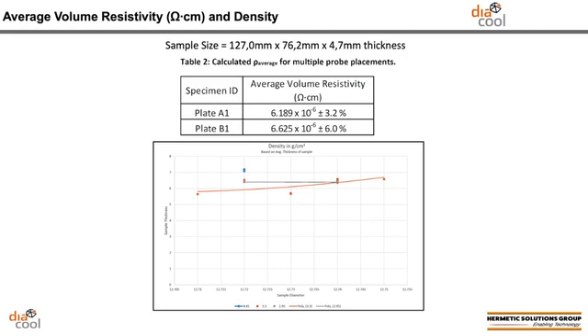At the bottom part of this chart, you'll see the density of the material. In this case, density in grams per cubic centimeter. You can see across the curve, this product sits right around 6 grams per cubic centimeter. Just as a point of reference, copper is around 9 grams per cubic centimeter.